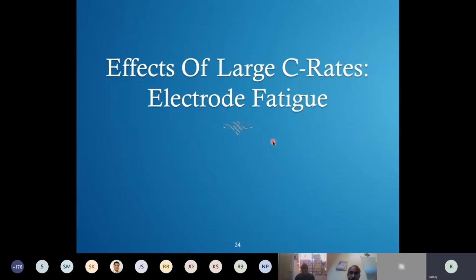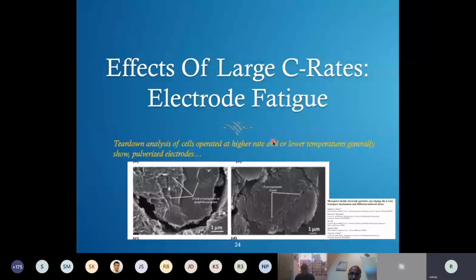What people found is that when they try to cycle the cells at higher C rates, they will see the electrode particles cracking inside. The electrodes are made up of these particles which will break over time, and typically they will see it at higher rates and lower temperatures, where electrode particles will totally pulverize. So we wanted to understand why it would happen.